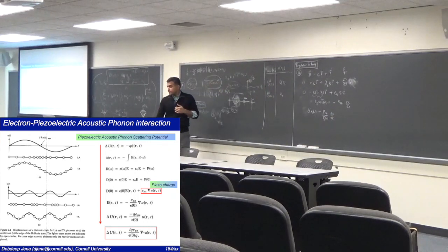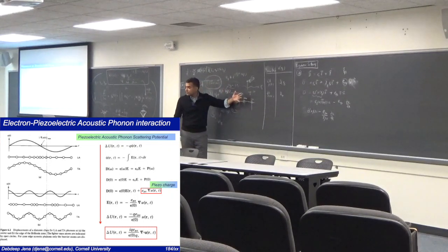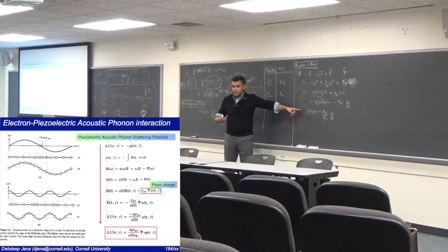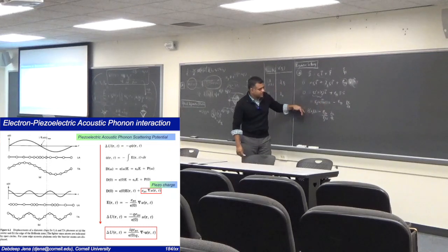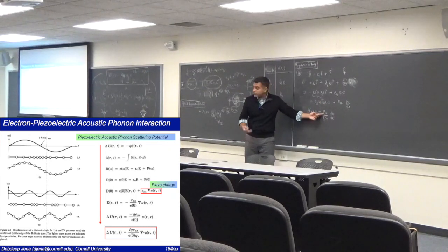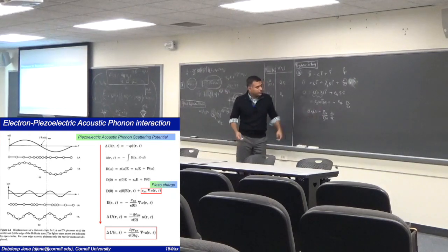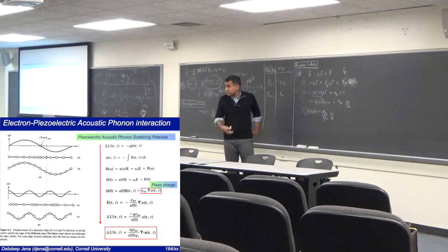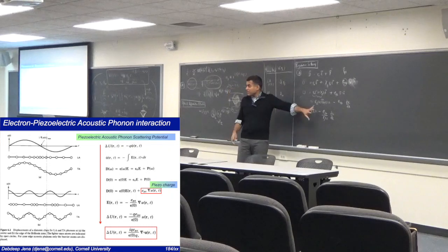That's the electric field. So when the phonon wave goes through the crystal and the atoms are slightly ionic, this is the electric field it creates. As it moves through, the strain multiplies by that coefficient and creates this electric field. For silicon, E piezo is 0, so there's no such thing. Does that make sense? For gallium nitride, it's actually very large. It's an extremely piezoelectric material. And crystals like lithium niobate and barium titanate are very, very high, even 10 times higher than gallium nitride. Gallium arsenide is about 10 times lower than gallium nitride, and they have a whole hierarchy of more and more polar crystals.